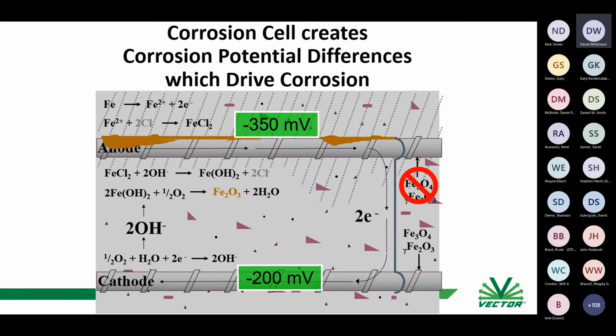And in that scenario that we just painted, the steel immediately to the right or left of that crack is probably going to be cathodic, not corroding relative to the crack. Why when you fix it, then the stuff that's nearby gets better. Exactly. When you fix it, it just pushes the problem further away, right? And we'll just get into that here in a second. So yeah, these voltage differences within the structure are what drives the corrosion cells, and ultimately we can use them, if we understand what's going on, for protecting the concrete as well.